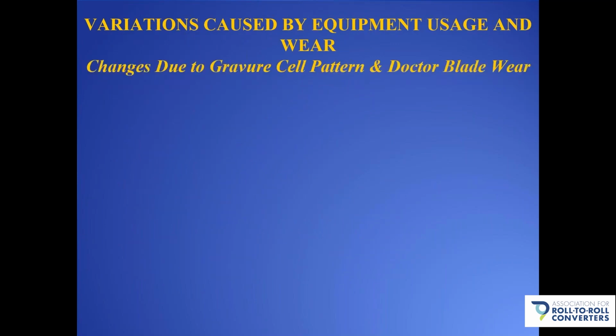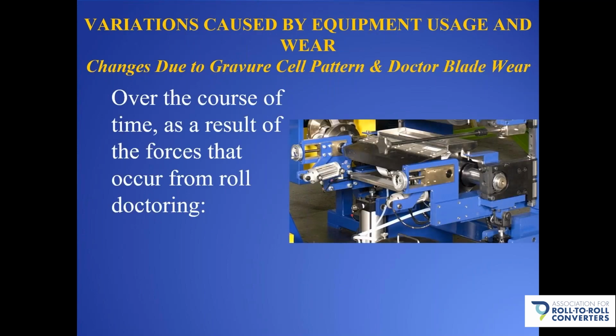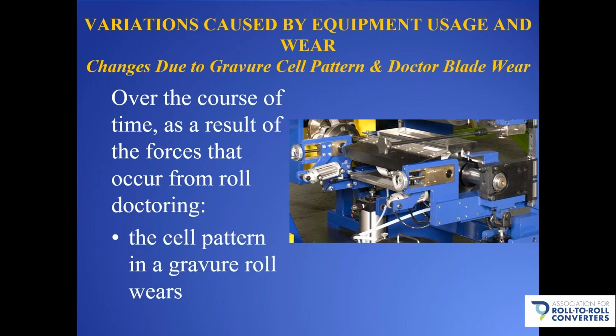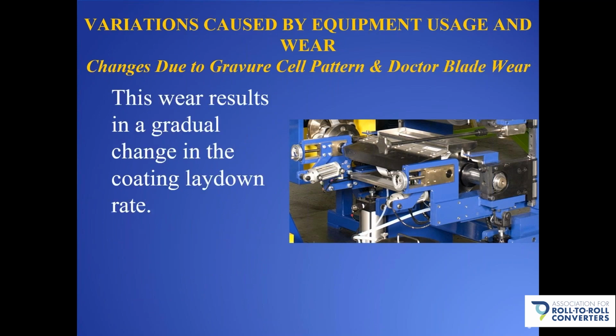Another issue that comes up is changes due to gravure cell pattern and doctor blade wear. So over the course of time, as a result of the forces that occur from roll doctoring, the cell pattern in the gravure roll wears, and the doctor blades wear. And this wear results in a gradual change in the coating laydown rate.